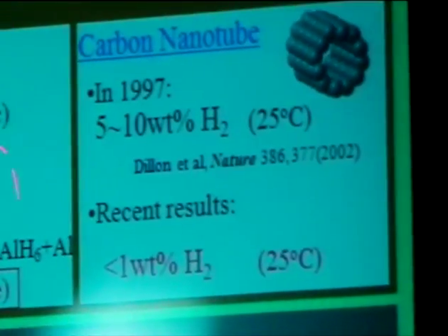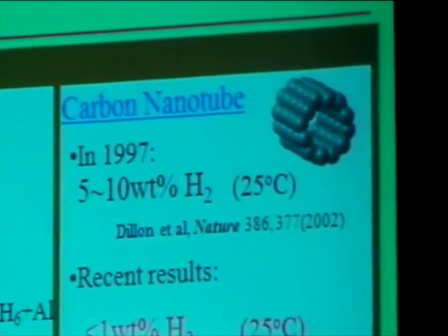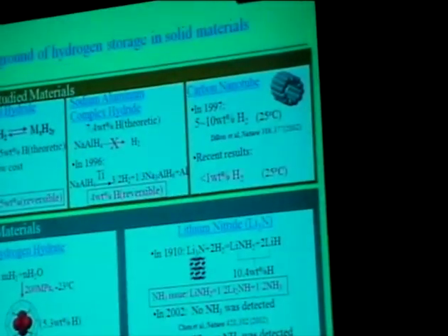Another important example that drew attention is the carbon nanotube. In 1997, one paper was published in Nature from the National Renewable Energy Laboratory. They reported that 5 to 10% of hydrogen can be stored at room temperature in nanotubes. At that time, that paper caught much attention worldwide. Many people thought the nanotube was a magic tube that could absorb so much hydrogen at room temperature. But unfortunately, in the past 5 years, many independent labs confirmed values below 1%.